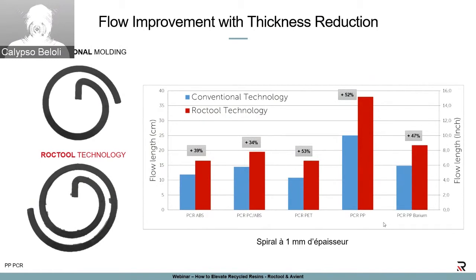So here you have some examples of PCR and PIR resin that we have evaluated with our spiral mold, in order to show you how much we can improve the flow and maybe the capability to reduce some thickness of parts. So the trials have been done with a spiral mold at 1 millimeter of thickness. And as you can see, for ABS to PP, we have a huge improvement of the flow. And that is very interesting when you have a project and you are looking for thickness reduction. That could be done using recycled resin. So it's a good combination for some projects.